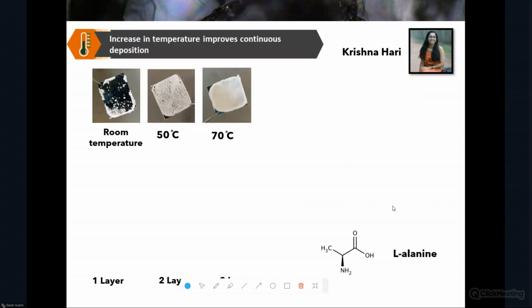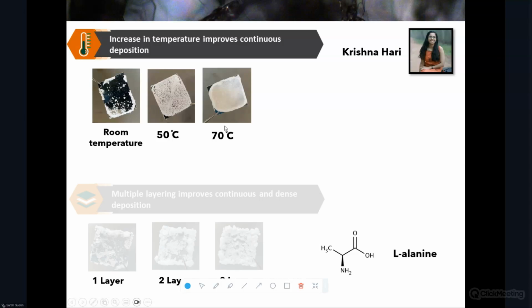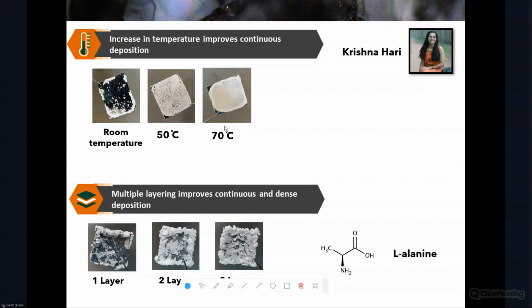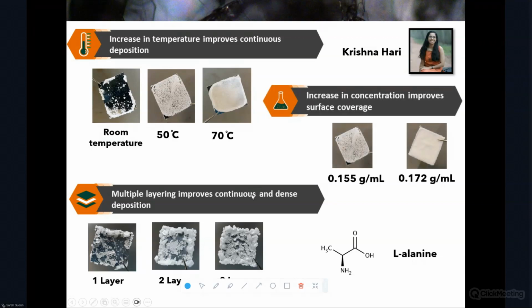So this is work that my PhD student Krishna has been doing in our group. She has, in the past 3 years, gone from this very sparse, low-density crystallization onto a bottom electrode. By controlling just our simple crystallization parameters, the temperature at which we're carrying out our supersaturation, layering, which you can see is still a bit messy, but we were asking if you deposit more solution onto a solid state crystallized assembly, does that increase the density? And then by optimizing lots of parameters, we get this lovely, textbook what we're looking for for device applications: a continuous, dense, semi-orientated at this point, polycrystalline film.